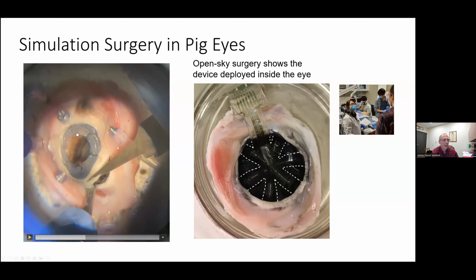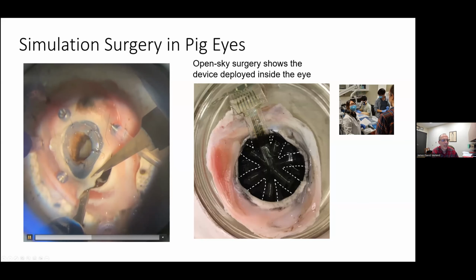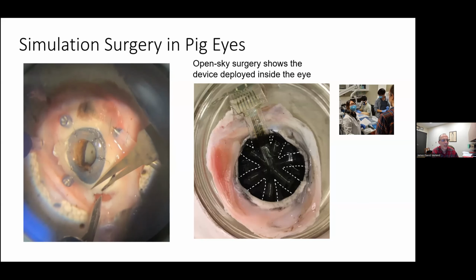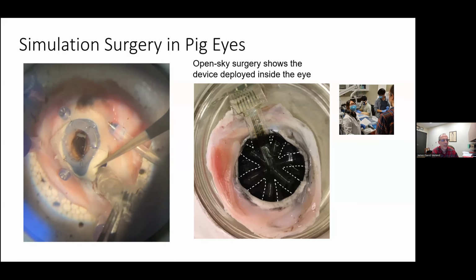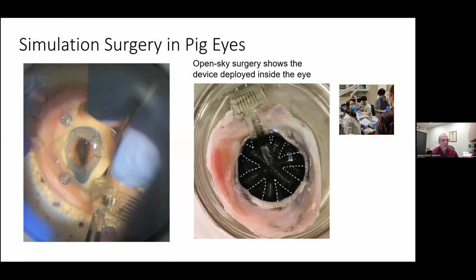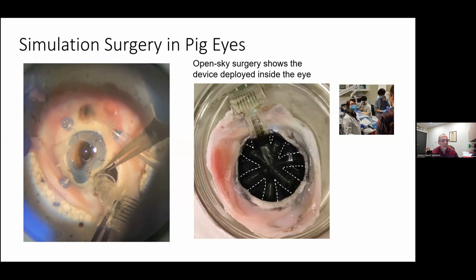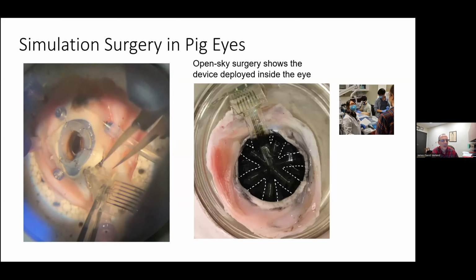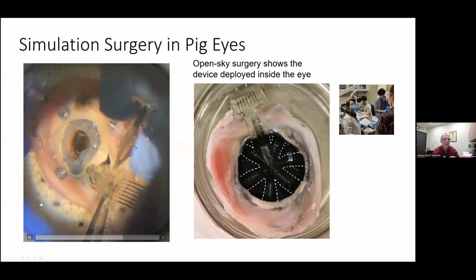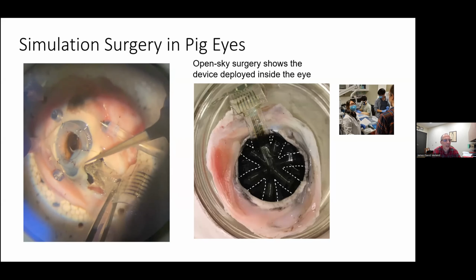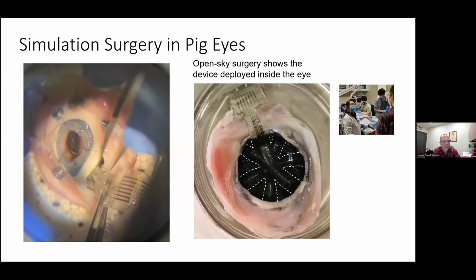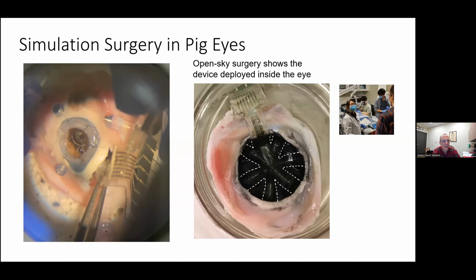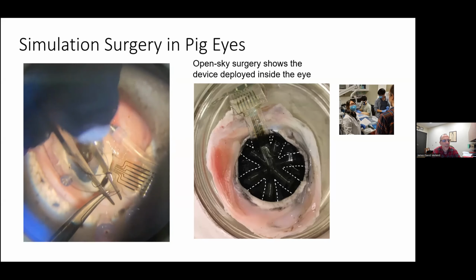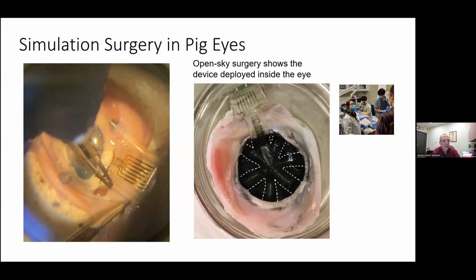So one thing we put in is a keratoprosthesis. This is an artificial cornea so that we could see to the back of the eye. And here we are making a very large sclerotomy, which would probably be unacceptable in a patient. But through that, he's able to insert this array. And it's dry, but once it gets in the liquid environment, the hydrogel will begin to swell. It's also been wrapped with a dissolvable material, polyvinyl alcohol, to hold it in place. And he's going to suture it closed.